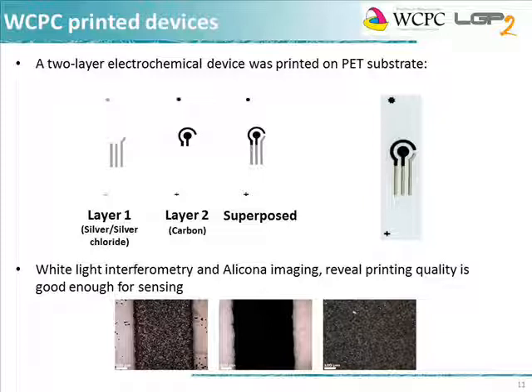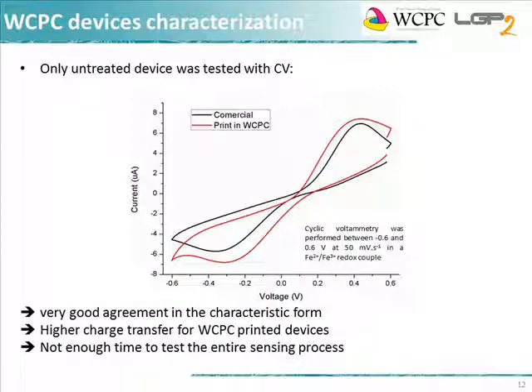for the sensing part. The WCPC printed electrochemical sensor were characterized again using CV, however, due to time issue, it was not possible to proceed with all the process of antibody antigen sensing, and only the untreated device was compared to commercial one. The performance of the raw WCPC sensor design was found to be better than the commercial counterpart, as the charge transfer is higher. Furthermore, it supports the replacement of the platinum counter electrode with a lower cost carbon counter electrode.